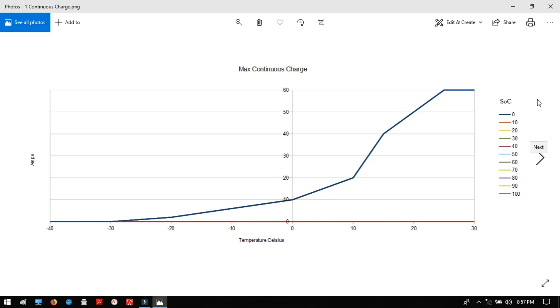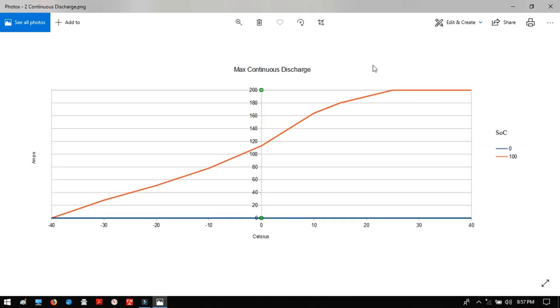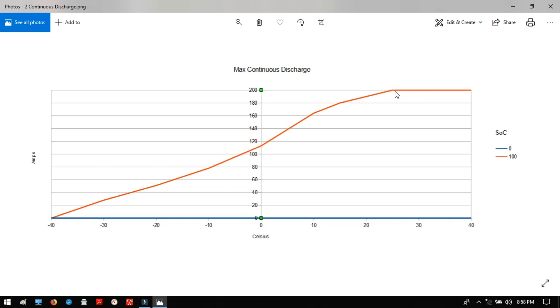Now, if we move on, the next slide here is the max continuous discharge. And we see something very similar. So we have the two extremes of state of charge and it's still Celsius and amps. And again, as it gets warmer, the chemical reactions like the chemical reactions in your fridge, they can happen faster and so forth. And so you can do more amps. So at zero, it's this. And by the time you get up to about 25 degrees Celsius, it's up to that 10C point that it can do, 200 amps there. But I should be decreasing this as it gets colder. If I don't, I'm putting extra, I'm pushing on the battery much harder and it will wear faster because of it.